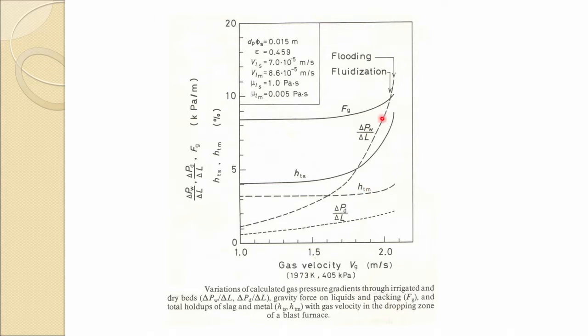And under this situation, your slag and metal would be going up into the higher zone of the blast furnace, which is cooler, and they will solidify, and more problems will occur then in the upper zone. So, maldistribution of gas and other things will occur, and it will block the pores in between the particles and will further reduce the permeability of the blast furnace, and the blast furnace performance will deteriorate. Which is not a good thing, but it predicts a trend in a good way.